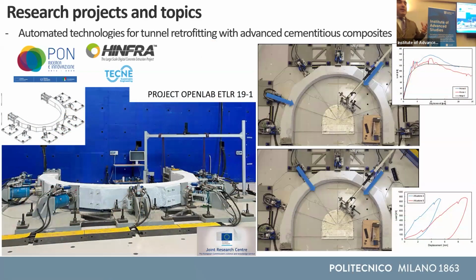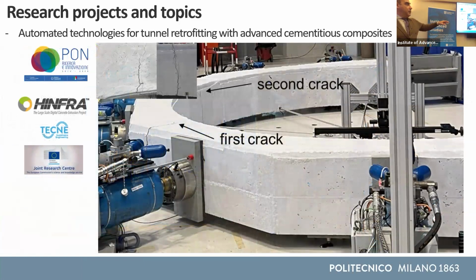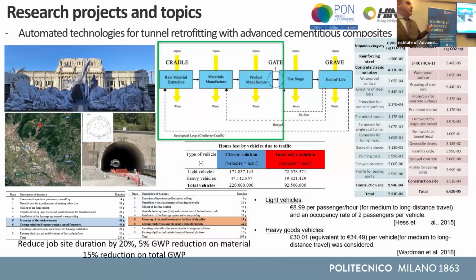And in order to bring this to the real application, we had to validate it with real scale testing. So these are 5-meter diameter mock-ups of tunnel vaults that we tested in different load combinations in the JRC lab of the European Community near Milan. We analyzed the cracking. This is only fiber reinforced concrete. And we went to a real site. This was about a 150-meter tunnel on the highway. We demonstrated that using this technology, we saved 2 months on the construction site time.